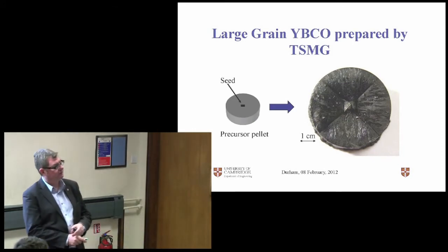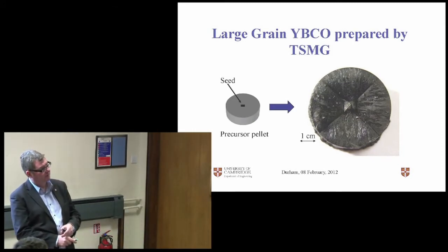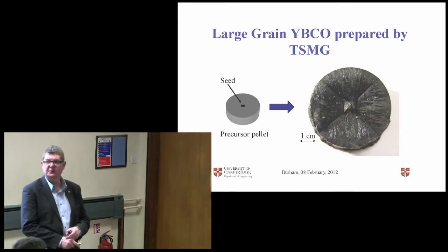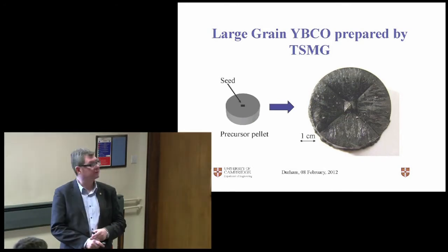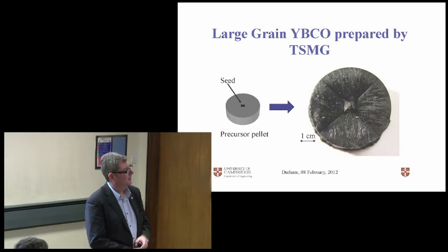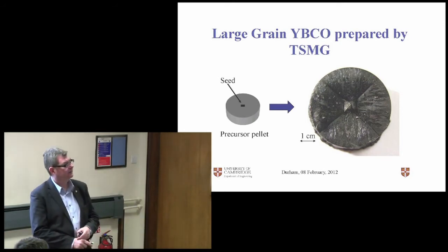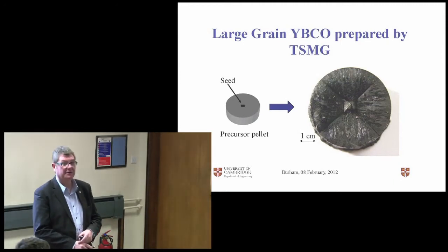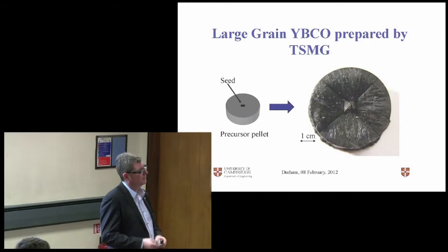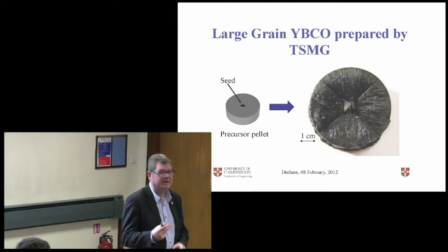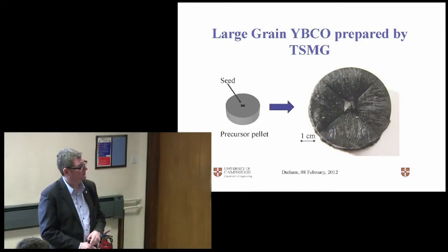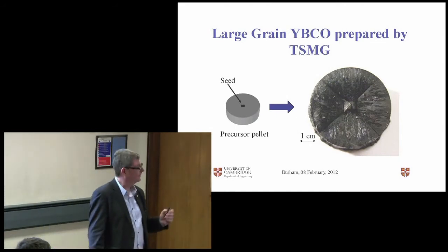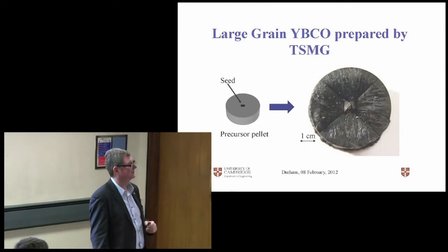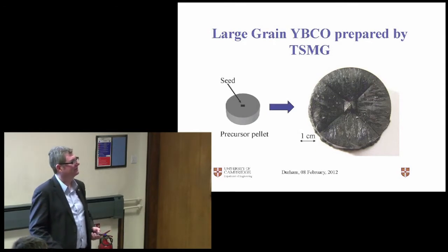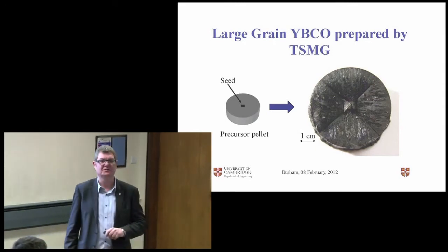So this is 3 centimeters diameter. Here's our seed crystal. We see the 4 facets. That tells you of crystallographic integrity. They're not grain boundaries. And even though I've seen many thousands of these samples now, I'm still amazed by just actually their beauty. And maybe I should have brought one with me, but they're just spectacularly attractive. It has been speculated they make a good contribution to the jewellery industry, which is kind of an insult given the effort you put into making them, but they really are spectacular.